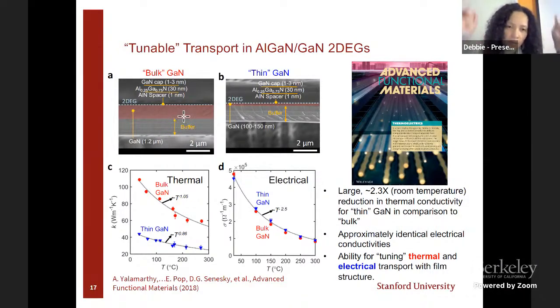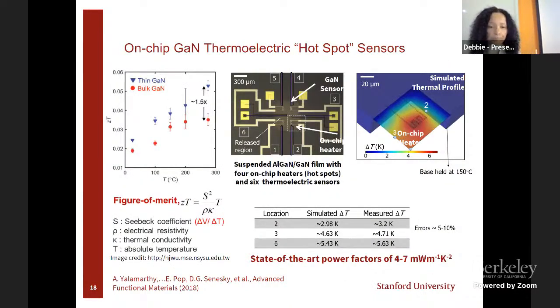So we have our thicker GaN, we're calling it our bulk GaN. We have a high thermal conductivity. And as we move to a thinner layer, we have a lower thermal conductivity, and that's due to thermal scattering between these interfaces. However, we're able to maintain electrical conductivity. That's the beauty of the 2DEG, the two-dimensional electron gas. We can still maintain our sheet density even if we change the thicknesses of those films slightly. So this idea of being able to tune the thermal transport and maintain the electrical transport. One figure of merit of thermoelectric devices is the ZT coefficient, where again we have a trade-off typically between electrical resistivity and thermal conductivity. And we show that for a thin gallium nitride, we get a boost in our ZT coefficient.